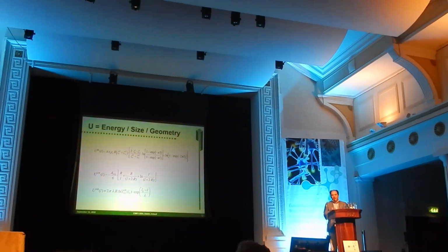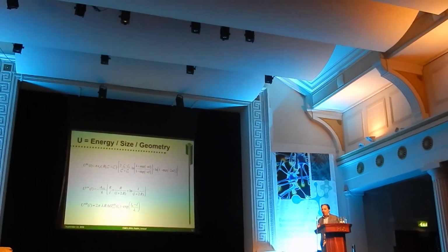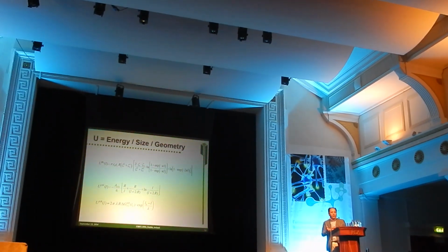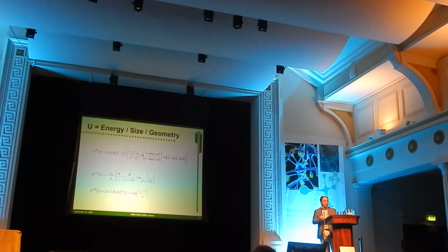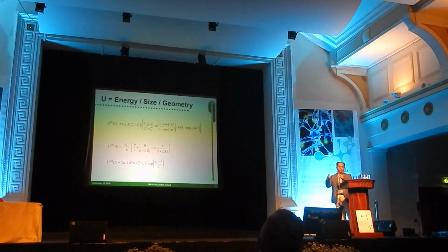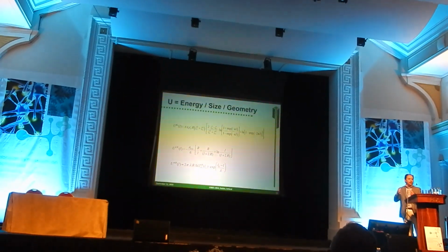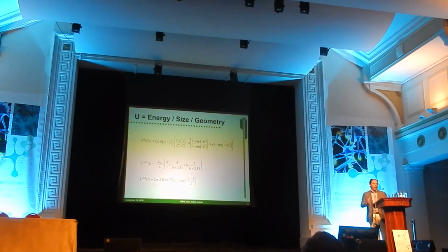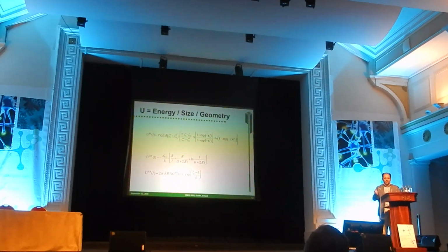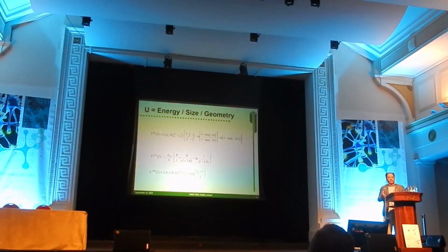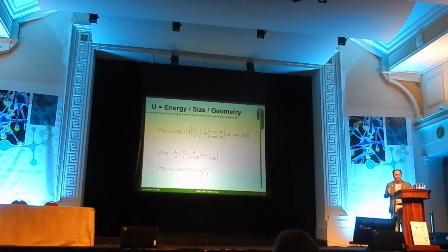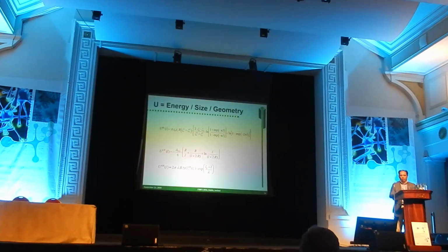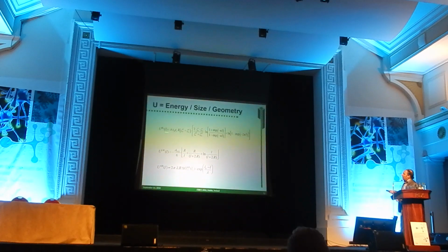So, at a certain distance, which is a couple of angstroms. We have to bring this to the real situation, and the real situation here is a small particle, the cell, and a big particle, the adsorbent. So we can have an additional simplification here and say, okay, since the radius of the adsorbent particle is pretty large compared to the cell, a 20 times difference, we can consider the big particle to be a planar surface, and then the only radius that enters the calculation is the radius of the cell. So this simplifies a lot, and if you look here, basically you can see that